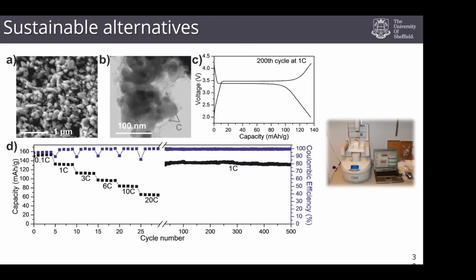And when we look at this material after we've cycled it like this, we find that the lithium and the iron don't start to exchange positions, they stay where they were meant to be. So we think this way of making materials is really neat. It also takes 3 minutes, down from 24 hours. So we can make the same very high performance materials in a very, very short amount of time. At the moment, we're only making a gram of it. We haven't tried to make any more. But the challenge now will be to move to scale. And that's what our next big project is looking at.